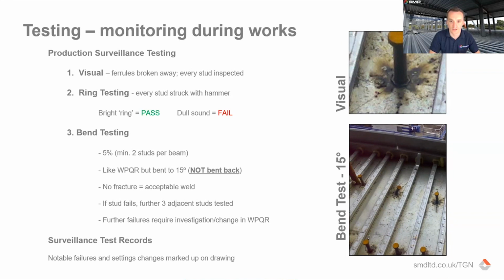You've then got, okay, are the settings I'm using continuously working during my shift? So that's what's called the product surveillance testing. So it's just monitoring that the works are going ahead and the studs are continuing to weld to the beam as required. So there's 3 test processes in that. Visual, so you break the ferrule away and inspect the weld, like in this scenario. Ring test, so the second stage, which I didn't have an image of, would be someone hitting a stud with a hammer. So you basically go around every stud, tapping it with a hammer, and you get a ring, shows it's passed.